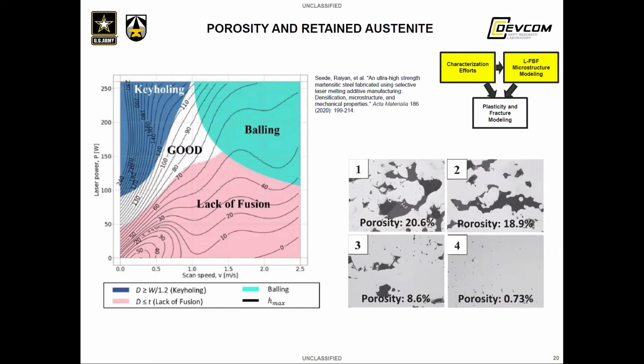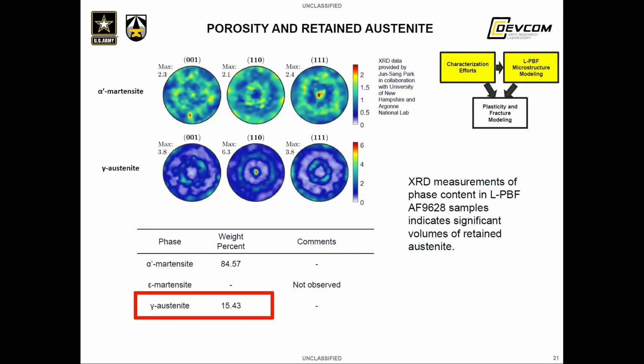Next, this experimental data was gathered for an AF9628 sample via X-ray diffraction. This data shows a significant proportion of retained austenite in the material, which is austenite that never transforms to martensite but remains stable at room temperature. In this case, roughly 15% by volume of the material remained as austenite and didn't transform into martensite. The texture of both the martensite and austenite constituents in this sample are shown by the pole figures above. Retained austenite in this form often can be transformed when the material is deformed. So this affects the hardening behavior of the material as the transforming austenite regions contribute to local plasticity. This is known as transformation-induced plasticity, or TRIP for short.